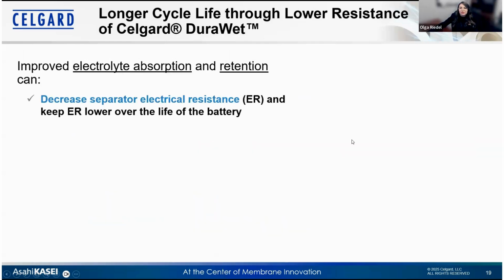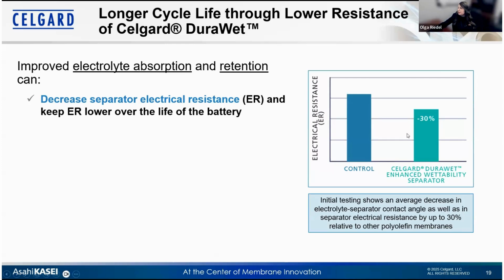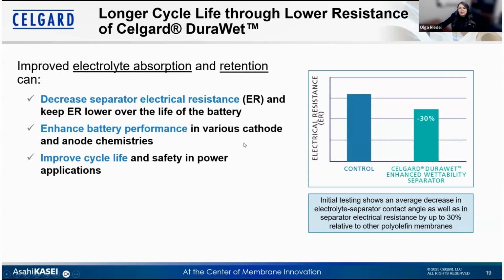So with this improved electrolyte retention and absorption, we can actually decrease the electrical resistance by up to 30% and keep the electrical resistance low over cycle life. So this helps to improve the cell performance, the cycle life, but also the safety.